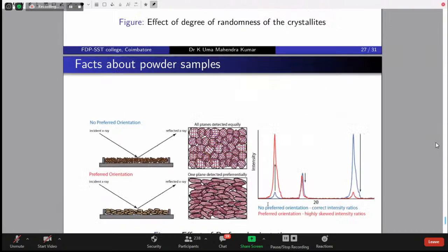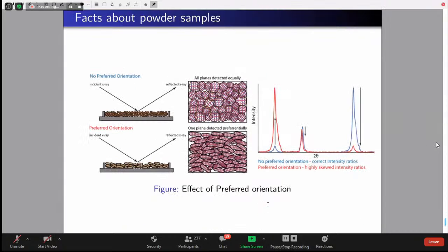Right. The other case of problem is preferred orientation. This is a major problem in thin films, but in the powder case, it should not be. Where you could see here, this is very randomly oriented. There is no preferred orientation in this sample. So we will have nice peaks which we got.